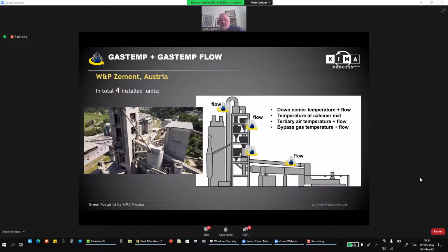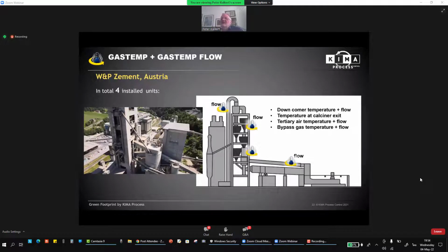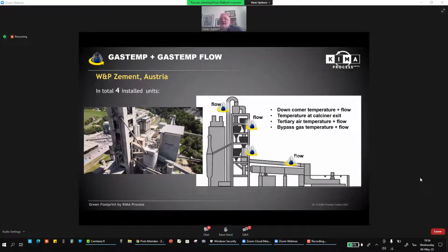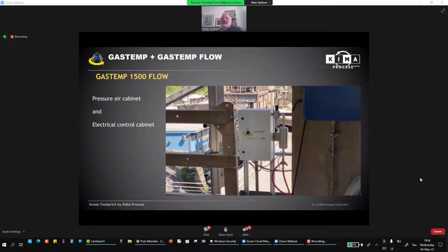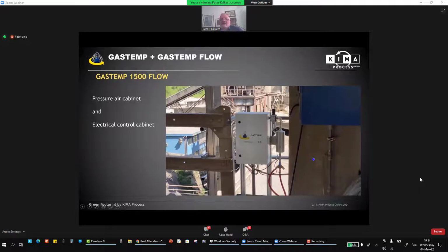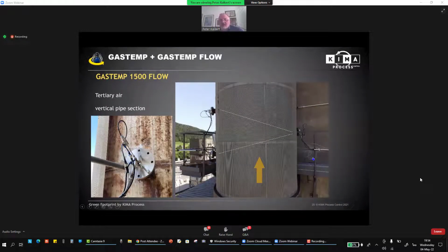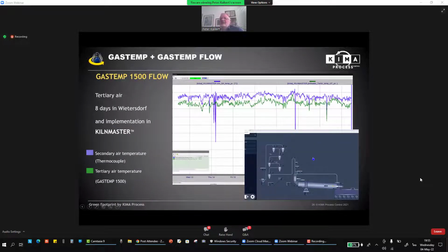And we have another example which I would like to go through pretty fast now. Here we have installed 4 systems at various locations of the kiln, and they are currently all working. And here once again is tertiary air flow, where we have temperatures up to 1000 degrees centigrade. And you can see them here. Secondary air temperature is blue. Tertiary air temperature is green. Pretty nice parallel, as would be expected.